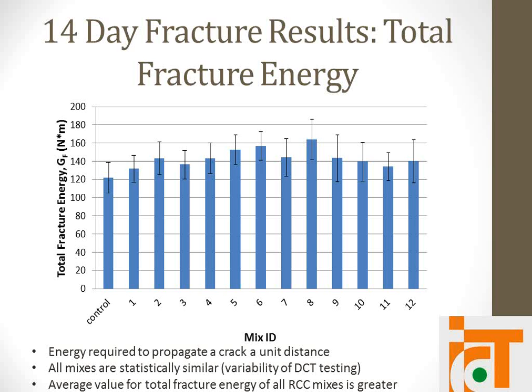You took away my initial question by mentioning that you were planning on investigating the effects of gyratory compactor. So my second question would be, in a room like this, with a bunch of pavement engineers, it tends to be black versus white, or PCC versus HMA. You've shown that this has the potential to perform at least as well as conventional PCC, possibly even outperform. You briefly mentioned the cost. Do you have any idea how the cost of this material compares to conventional PCC or even HMA? For concrete, I think it's about 70 to 80% of typical PCC. Asphalt, I'm not sure, depending on oil prices and whatnot. And it's typically used as a composite pavement due to its poor surface finishability. So in all the studies that I've seen, it's typically anywhere from 6 to 10 inches of RCC with a 2-inch asphalt surface course.